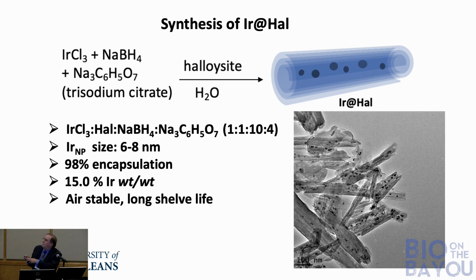Okay, what's important to note from this slide is we don't have nanoparticles floating around out here. So all the nanoparticles really get inside the tubes and we get good encapsulation. This particular sample, under the conditions we use, gives us about a 15% weight of iridium relative to the bulk material. Okay. Turns out this adds to stability, has a long shelf life without loss of reactivity.